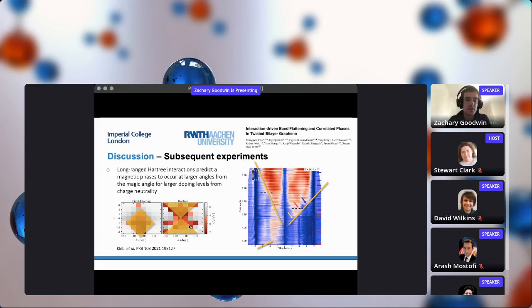And in fact, subsequent experiments that were performed this year found that our Hartree picture was the closest to the experiment. So for angles significantly larger than the magic angle, the correlated insulating state at plus 3 electrons is first observed. When the twist angle is closer to the magic angle, we then get the onset at plus 2, plus 1. So the experiments confirmed one of the main qualitative predictions of our theory.